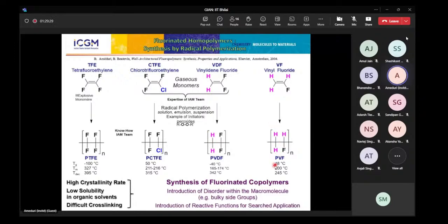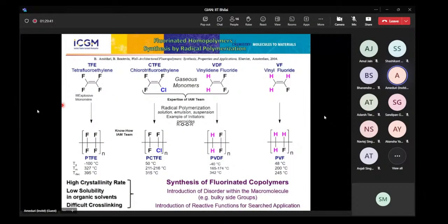And then polyvinyl fluoride, which has a Tg of 48 Celsius, and a melting point of 200 and a degradation of 245. So just keep in mind, this monomer can be polymerized or even copolymerized under radical polymerization with persulfate or peroxide in different processes, can be in solution, in emulsion, in suspension. They have a high crystallinity rate and they have low solubility in organic solvent. PVDF can be soluble in DMF, DMSO, and NMP. And they have a difficulty of cross-linking. Cross-linking means you want to enhance the properties. So you need an autoclave.